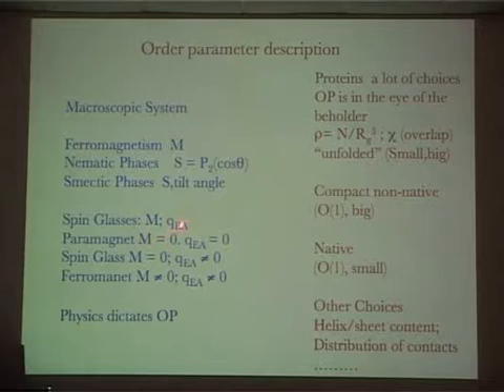You need 2 order parameters, much like the folding reaction. One is M itself, and the other one is a so-called Edwards-Anderson order parameter Q. M is 0 and Q is 0: that corresponds to the paramagnet. Spin glass phase, M is still 0. No average magnetization, but the Edwards-Anderson order parameter is non-zero. And in a ferromagnet, they both are non-zero.